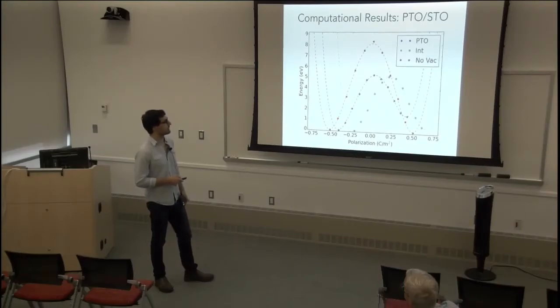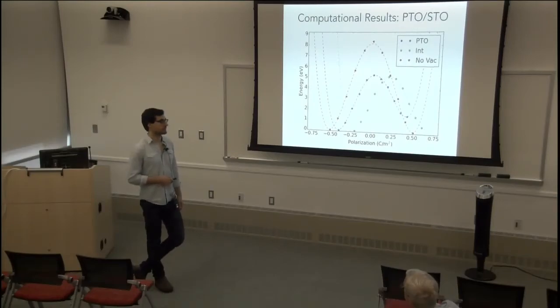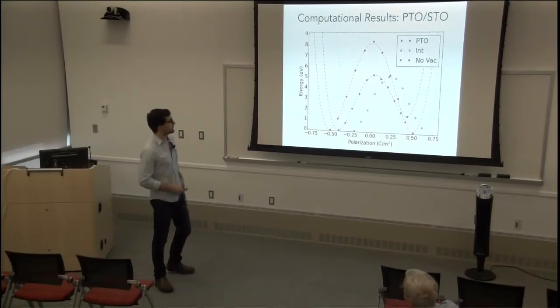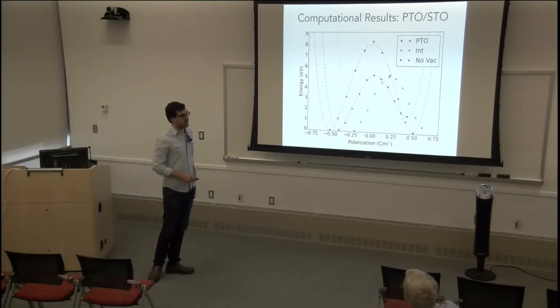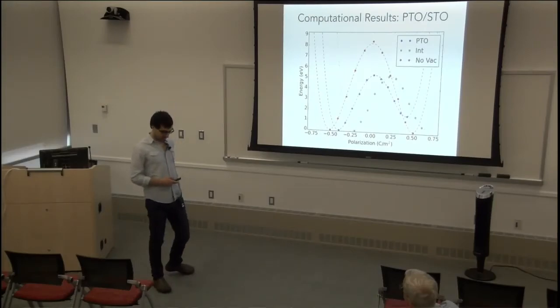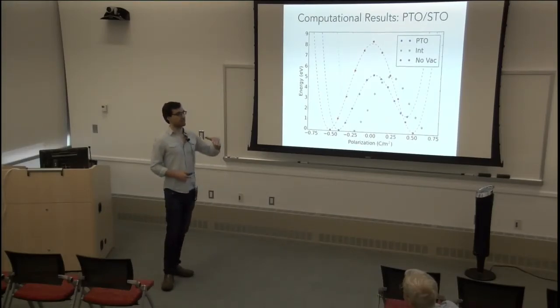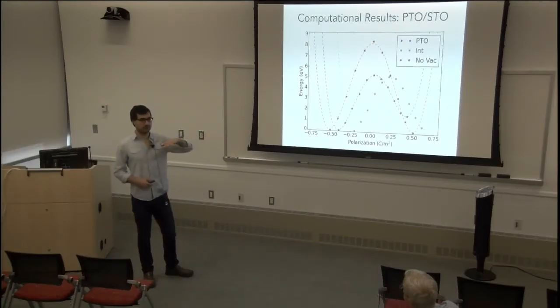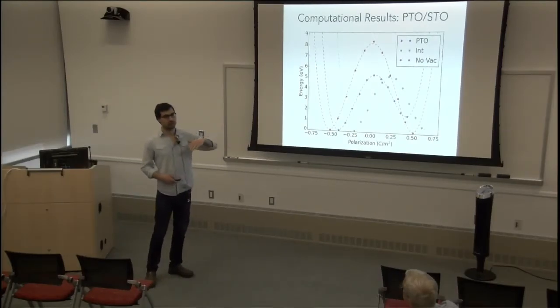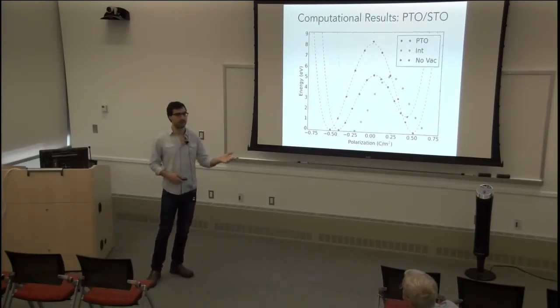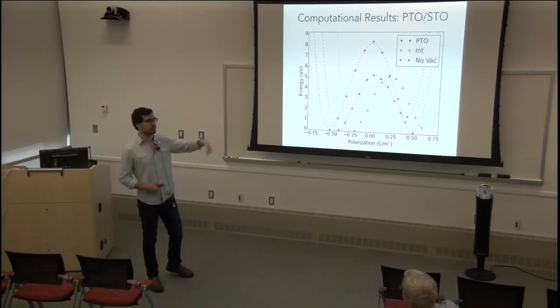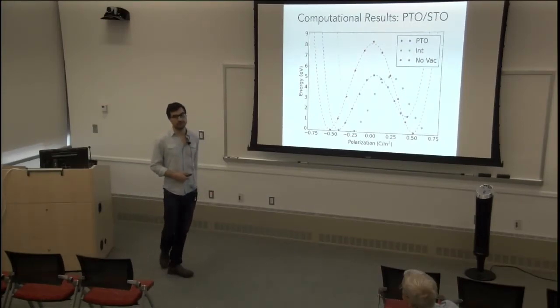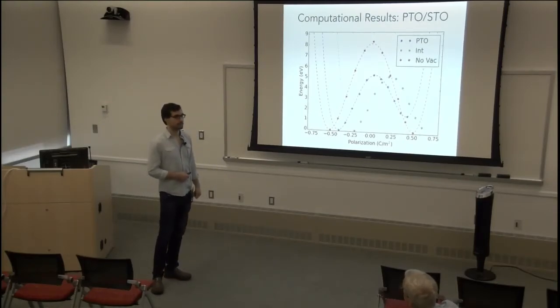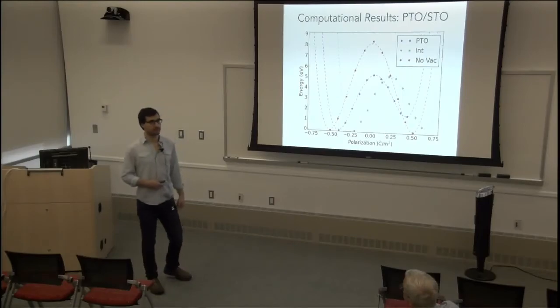Can any property of these Ti vacancies be measured? Can you count them experimentally? Well, they do have an approximation of the amount of Ti vacancies, but it's not something they can see, because they can only see an average of what's happening in the superlattice. So on average, you wash away the Ti vacancies. You could never actually see them with an electron microscope because you just look at the average intensity of the plane, for example, the average intensity of the atoms. But does that tell you the total number in the sample? Total concentration? Yeah,